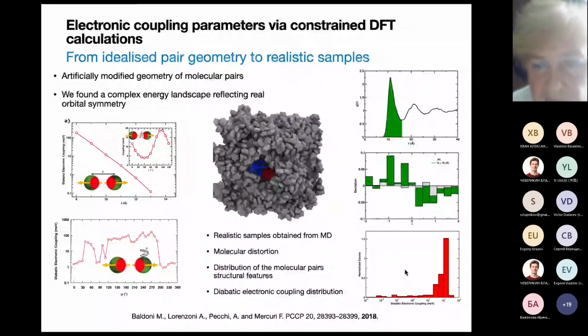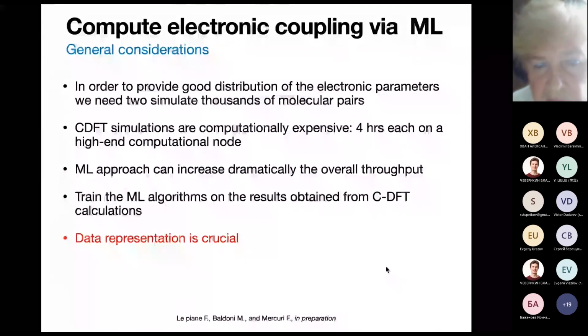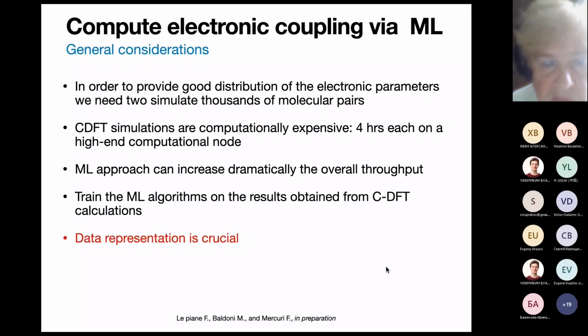In order to provide a good distribution of these electronic parameters, we need to simulate thousands of these molecular pairs. And even though our implementation is quite computationally efficient, constrained DFT simulations are relatively computationally expensive. We need at least 4 hours for each pair on a high-end computational node. So we do believe that a machine learning approach can increase the overall throughput dramatically. We want to train our machine learning algorithms on the results obtained from constrained DFT calculations.